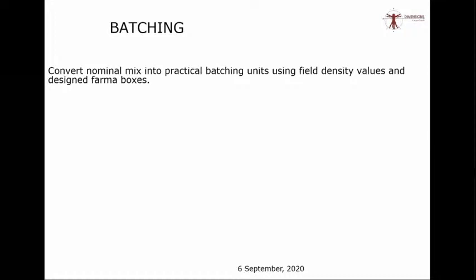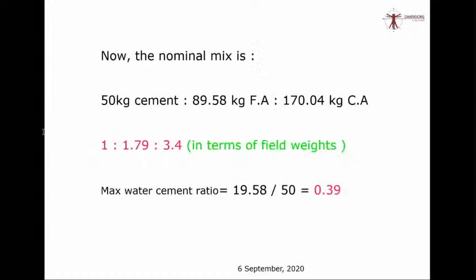When cement exceeds a particular amount, a little bit of extra cement is no harm. But if you keep on adding more and more cement just to achieve more quality, actually it will deteriorate the quality, because cement is a highly shrinkable material. It will form shrinkage cracks very rampantly, and therefore you will end up losing strength and workability. So once you have arrived at this proportion, you should use proper batching techniques.